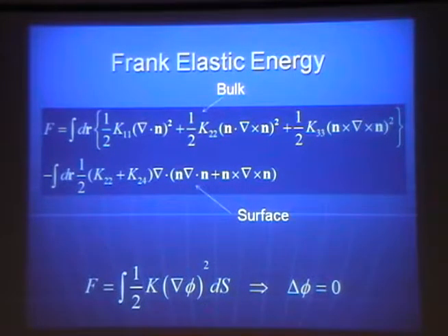And in a very simplified manner, when the liquid crystal follows the orientation of the surface with a planar orientation, as I mentioned before, in order for the saddle-splay contribution to survive, the Z component of the director must vary over the surface.